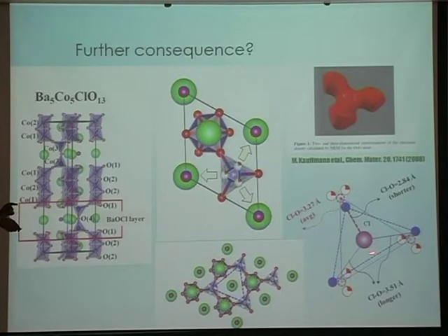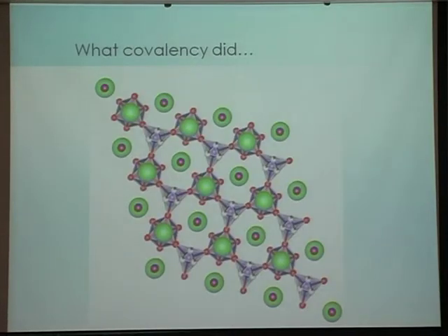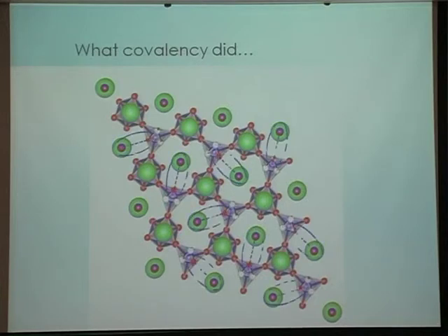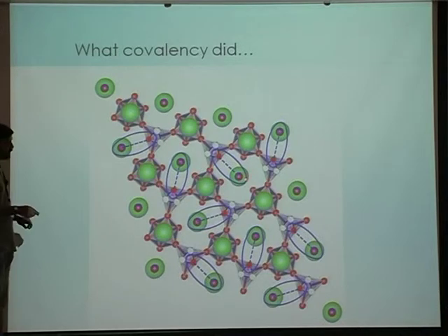What is this possibility? Every chlorine is finding one oxygen closer to it. That means this chlorine is finding, let's say, this oxygen sitting here. The other 2 are invariably away. So you have an asymmetric triangle, which is this blue dashed line. That's the reality. Every chlorine tries to pull in one oxygen. What's the net result of that? That's the average scenario. I go for a static positioning, and I have a situation like this. Every chlorine pulls in one oxygen around it. Every chlorine, all of them, like this.